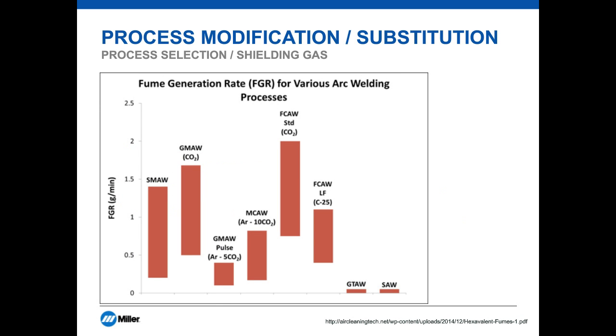This slide shows how changing the welding processes, and in some cases the shielding gas, can help to reduce the amount of fume that is generated. Processes such as gas tungsten arc welding and submerged arc welding tend to be very low in fumes. Unfortunately, gas tungsten arc welding is also very low deposition and requires a high degree of welder skill. Submerged arc welding, on the other hand, can only be used in the flat and horizontal position and may require a large investment in equipment.